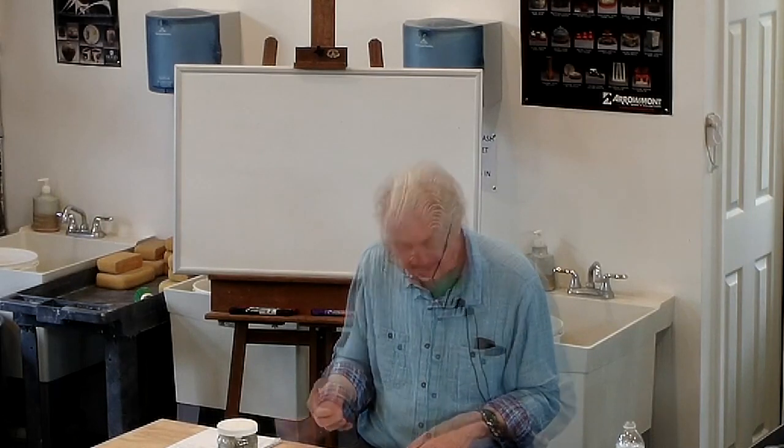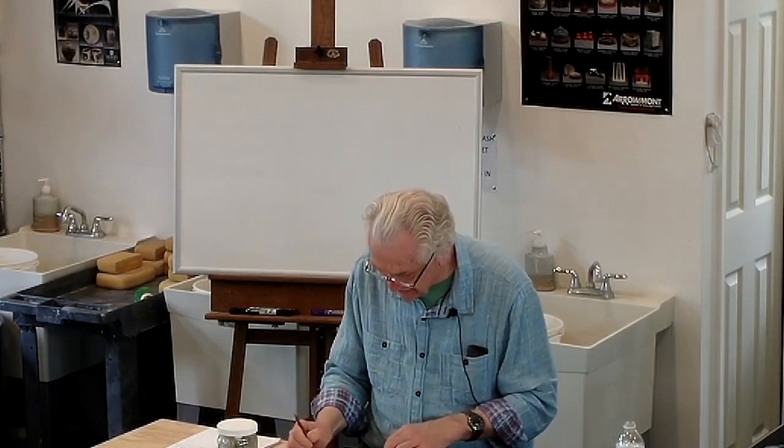Here's another one, St. John's Black, really simple, just nepheline syenite and Alberta or Albany slip. Albany slip is the highly colored slip that was dug around Albany, New York, and Alberta is the man-made substitute for it. It's a highly iron-manganese, highly colored clay. Anyway, I wanted to give you some, and then on the right, black. Here's another black glaze with Albany slip again, and whiting and nepheline syenite.